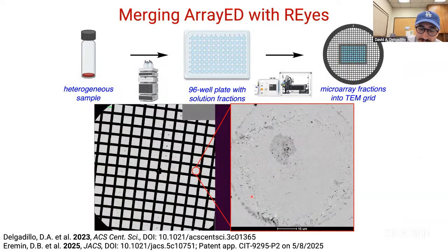And so the other thing that was really exciting to me was the application of screening, right, of identifying where spots can diffract, and how this could help me in my application from a throughput standpoint. So Mike mentioned how sample preparation is critical to a lot of these applications. And in 2023, we kind of showcased this ArrayED method, which kind of pairs MicroED with these DNA microarrays, so you can up the throughput of your sample loading. But when you get to load 96 different unique samples on a grid, the time that you spend screening for things that actually diffract goes up exponentially, right?